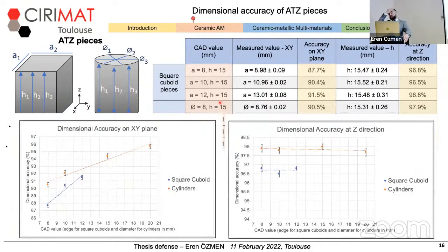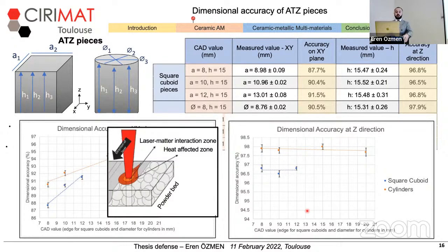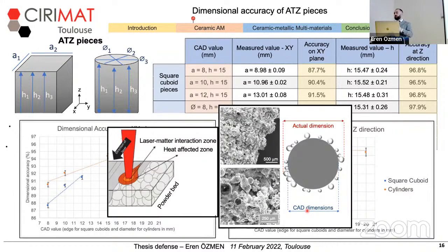When we see the dimensional accuracy on a graph, we can see that the dimensional accuracy is increasing with increasing surface area. However, the dimensional accuracy on the height is stable with increasing piece size. One explanation for this can be the laser-matter interaction. When the laser hits the surface, it creates a heat-affected zone. When the laser is processing the corners of the piece, and when we consider the spot size of the laser, the neighboring powders might be affected by this heat, and they can be included in the piece with sintering or necking between powders, as we can see here in the illustration and the observations.